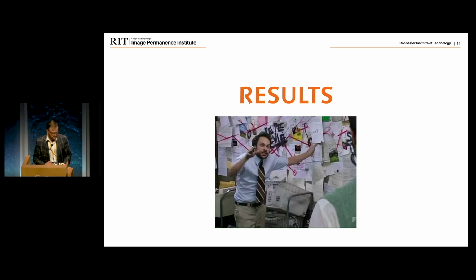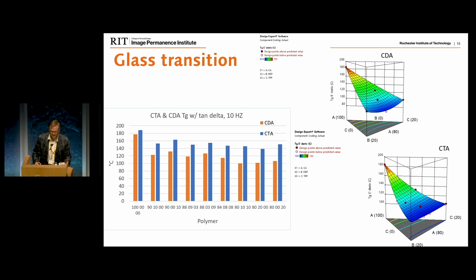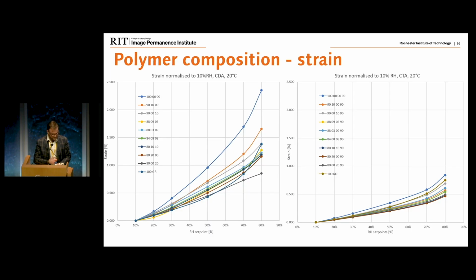So what are the results? In glass transition temperature, it's kind of simple. You can make those nice three-dimensional surface curves, but basically the very simple graph shows that you can see the impact both of the polymer composition and the amount and type of plasticizer on the response to those tests, which is going to be important in a second, because when you're looking at the influence of the humidity of different